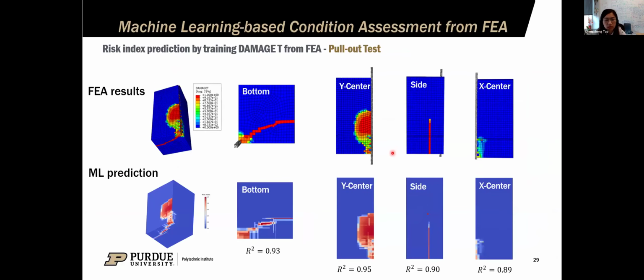We also use the pull-out test data from finite element analysis to train the machine learning and give a risk map for this pull-out test. And the R-square value is quite high, more than 0.9.